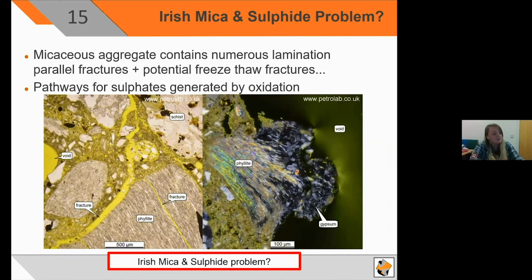So another thing to think about is the nature of the phyllite and other micaceous aggregates. There are numerous fractures, as you can see. You've got lamination parallel fractures here. You've got the big freeze thaw fractures throughout the binder. Some might say that this causes pathways in the binder for the sulfates to easily migrate. Is that possibly another reason for accelerated oxidation? And really, is this actually more of an Irish mica and sulfide problem?